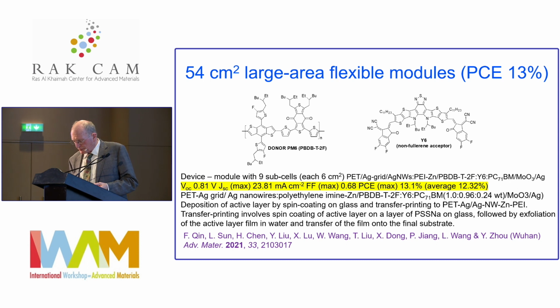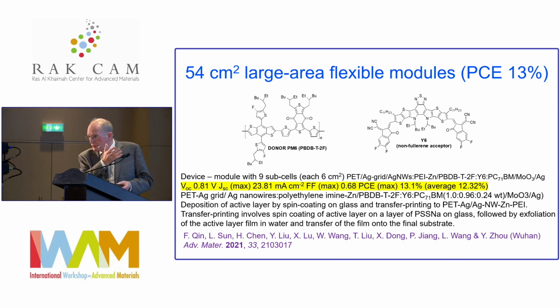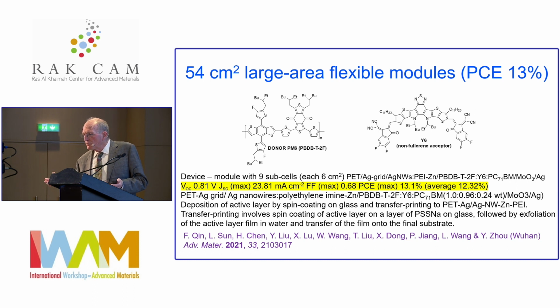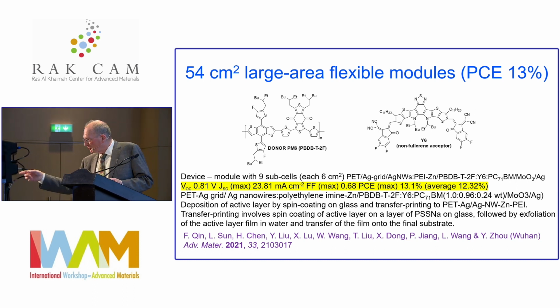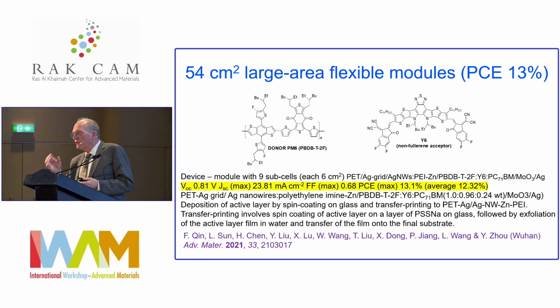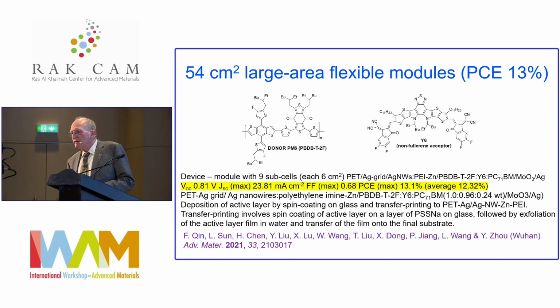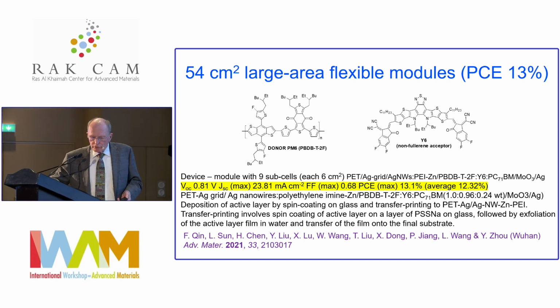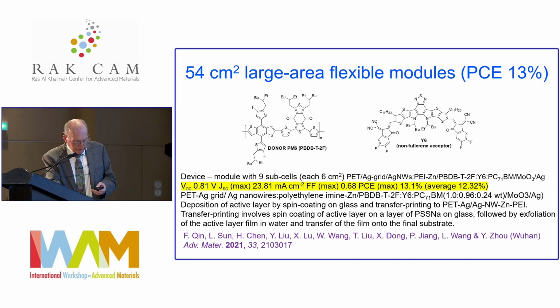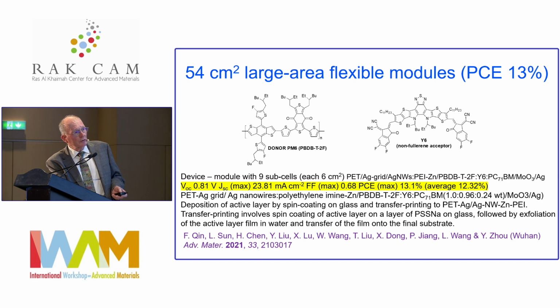The problem with these device printing is if you build this device up, as I showed in the example we had, you can't have any serious thermal treatment process to deposit the silver grid onto the top. You have to have it pretty much because the morphology, the PET, the polymer, the plastic, these aren't polymer bottles we've got here, but the plastic drink bottles that you buy, that's PET, that can't survive high temperature treatment. So you have to have a final process that is low temperature or lower temperature. And this way of floating it off and transfer printing it is one way around it. I'll show you an even more impressive alternative approach from CSIRO, the Government National Lab in Australia, our partners in all our solar cell consortium work, in a minute.